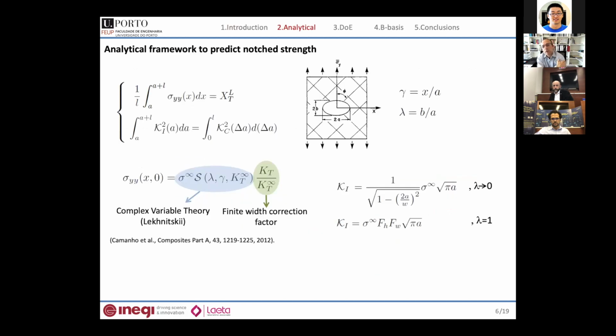So we are going to generate B-basis allowables for composite laminates with notches, okay? Of course we could solve this problem using nonlinear finite elements, but like I said, we're going to use a simplified model that we have developed and validated in the past, which is based on finite fracture mechanics. So if we take a composite laminate with a notch, and we have a notch geometry that is represented by this parameter lambda, and we introduce this non-dimensional variable gamma, we predict strength when these coupled criteria, a stress-based criterion and an energy-based criterion, are satisfied, when the system of equations is satisfied.